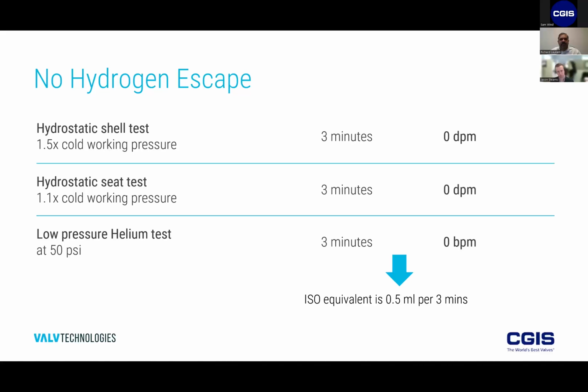The reason why a low pressure test might initially seem counterintuitive is that it's actually harder for a valve to pass a low pressure test than it would be for that valve to pass a high pressure test. The valve could be relying on the upstream pressure in order for it to seal. So by asking the manufacturer to do a low pressure test with helium, because it's safer than hydrogen and the molecules are almost as small, it's much harder for any valve design to pass a 50 psi helium test than one at a much higher pressure. But again, if we compare this with the ISO equivalent, it was roughly half a milliliter for that same 3 minutes of duration. So the point here is that if the factory has more stringent standards, the likelihood that hydrogen escape is going to happen decreases significantly. So the testing becomes quite important.